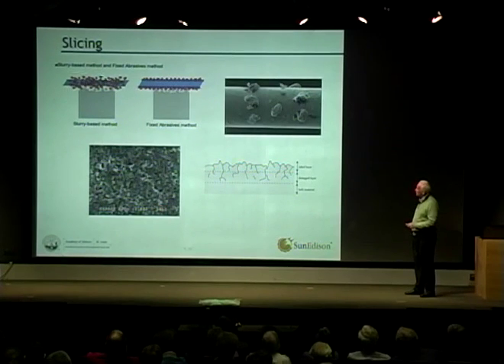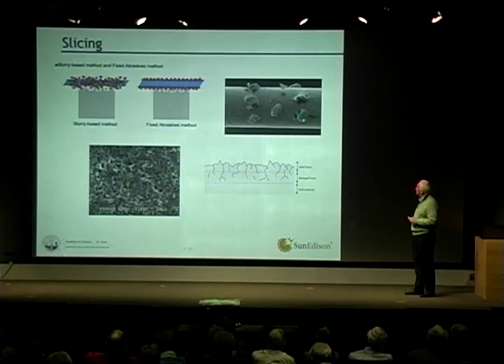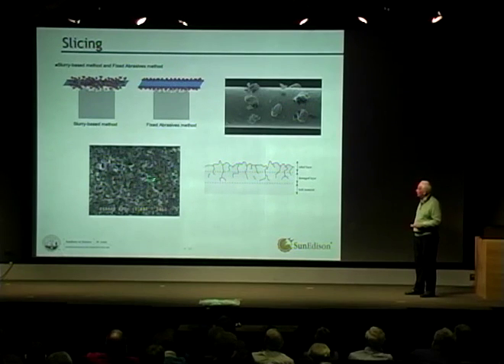Another recent development, and here's what's going on. This is called loose abrasive sawing, which is where we have the silicon carbide slurry, and we try to recycle that and reclaim the silicon carbide. Another thing you can do is take a wire that is impregnated with diamond. Here's a piece of that wire. It's a steel wire, sometimes brass coated or nickel coated, and diamond grains are impregnated in here and held in, and then you drag that across the surface, and the surface looks like this. I don't know how well you can see it at the back. Doesn't look very clear from here, but if this were brighter, you'd see that there are a lot of ups and downs, and there are also cracks which are represented here.